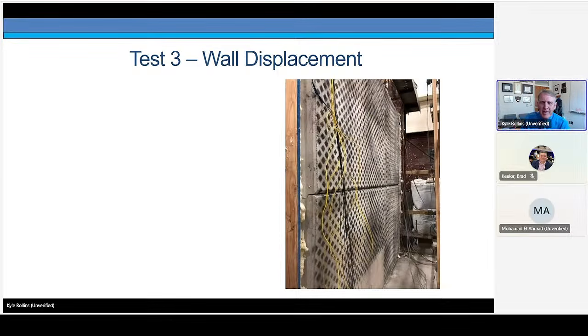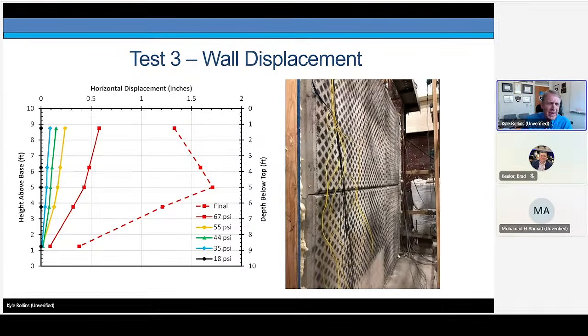What about wall displacement? This plot shows the displacement of the wall from the base to the top. Once again, we have to get up to a surcharge pressure of 55 PSI, fairly high, before we start to see more than 1/4 inch of displacement maximum on the MSE wall face itself, lateral. As it starts to get to the failure state where we have excessive deformation, you can see that we have a maximum displacement at the joint between the two wall panels. It still doesn't look that terrible, but there is a displacement of 1.7 inches at that joint. But we had to get to a case where we're almost ready to fail before we started to get a lot of excessive deformation. At this point, the reinforcements have failed in pullout, as you'll see later.